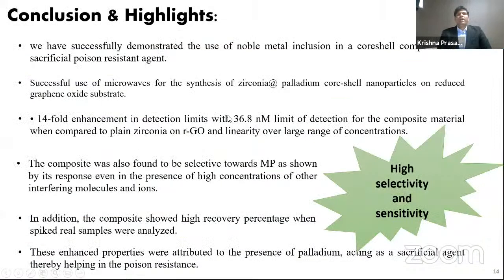And in conclusion, we have successfully demonstrated the use of noble metal inclusion in core shell composites as a sacrificial poisoning agent, which has resulted in a 14-fold enhancement in detection limits, with 36.8 nanomolar for the composite ZrPd RGO. The composite was also found to be selective and sensitive towards methyl parathion, as demonstrated by our interference studies. And in addition, the composite showed very high recovery percentage and high sensitivity and selectivity.